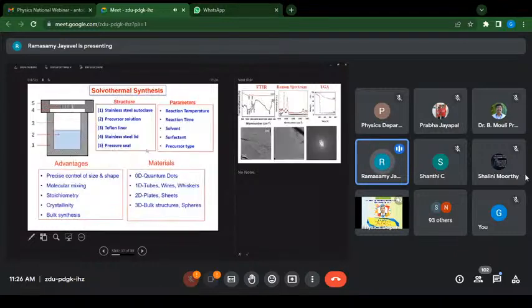So other than the chemical reduction process, we have solvothermal or hydrothermal synthesis, which needs a small autoclave, which can be operated at 300 to 350 degrees Celsius, where we can have very precise control of the size and shape of the structure. When we use high temperature and high pressure, there is molecular mixing, and this molecular mixing ensures the stoichiometry and also crystallinity. And not only for 2D materials, this can be useful for almost all 4 different forms of nanostructures, starting from zero-dimensional quantum dots to one-dimensional nanotubes, 2-dimensional sheets or plates, and then 3-dimensional bulk nanoparticles can also be prepared by solvothermal synthesis.